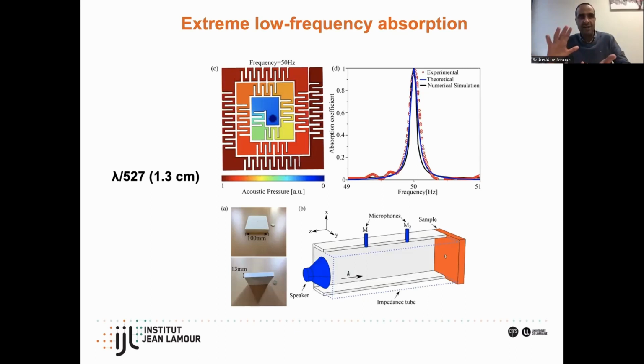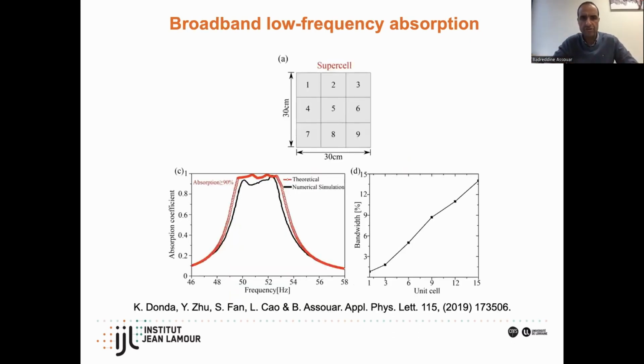In general, there are three key problems in acoustic absorption and three features that we need to realize simultaneously. We would like low frequency, we would like very low thickness, and we would like a broadband aspect at the same time. This is extremely difficult, but we are working on that. Here we have a very thin metastructure or metasurface, and we have a low frequency, but we don't have the broadband aspect. Of course, we realize this, we put that in a waveguide, and we make measurements based on dual impedance tube or B&K structures and so on.